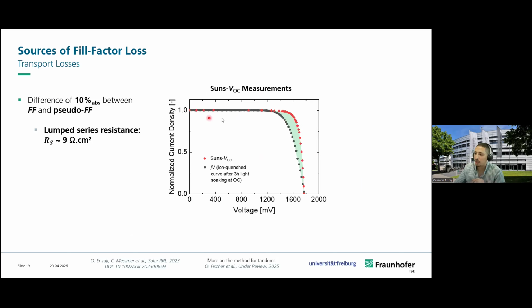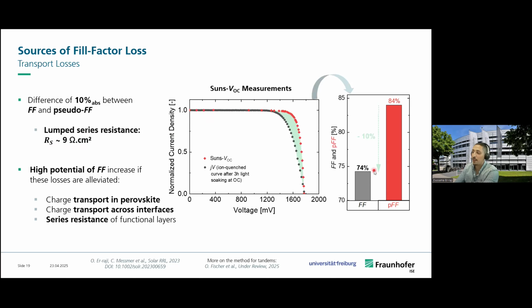And so coming here at VMPP, we can determine that the voltage drop at maximum power point gives us an estimation of the lumped series resistance, which is 9 ohm centimeter square. What we can also do is extract the value of the fill factor of this curve, the pseudo fill factor. And this tells us that our current architecture has the potential to achieve 84% fill factor if we reduce the losses due to transport, so transport in the perovskite, contact resistance, and series resistance across the different functional layers.